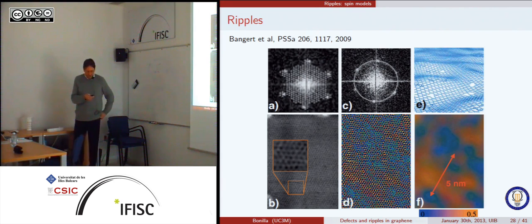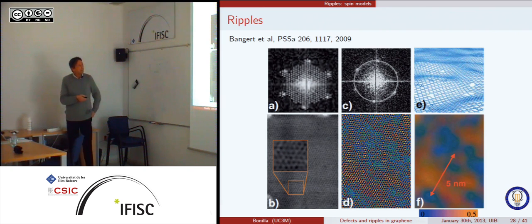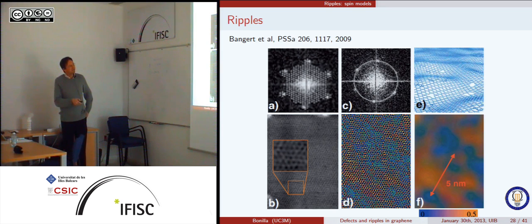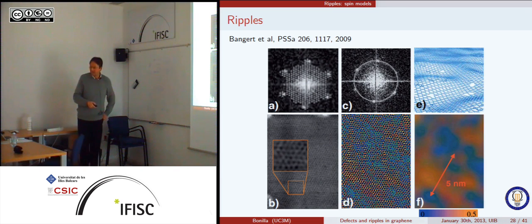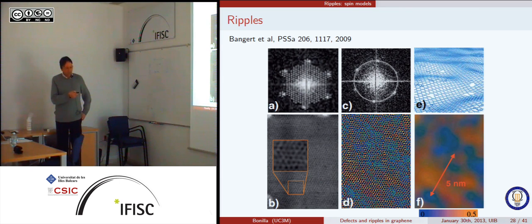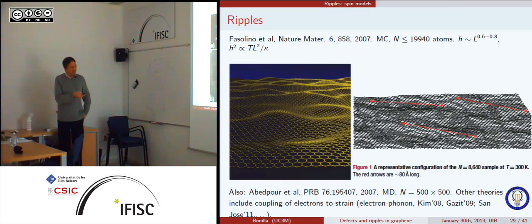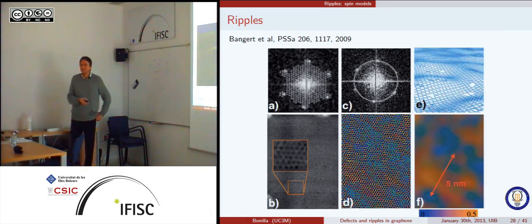Okay, so this is the other part that we did about the ripples. This is experimental evidence for the ripples. They are done similarly, so you Fourier transform these things. Now you treat the image so that the atoms that are supposed to be above the horizontal sheet are orange, and the ones below are blue. And then with that you get an idea about how the ripples are oriented, and what is more or less the wavelength. Of course, there may be ripples on top of the defects on top of the ripples, and this is some schematic diagram. So, sorry, 5 nanometers is the height of the ripple?